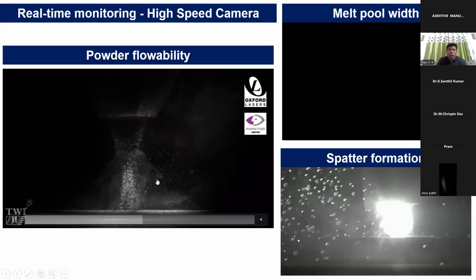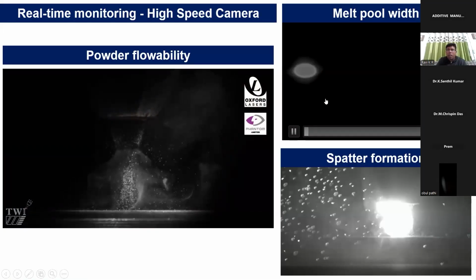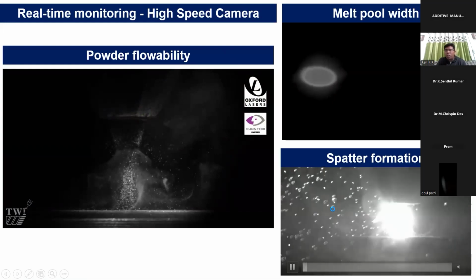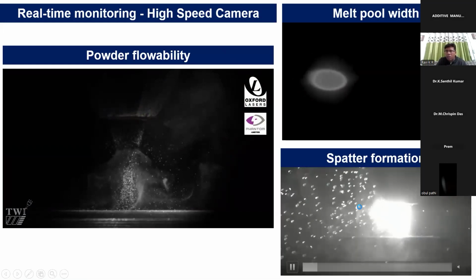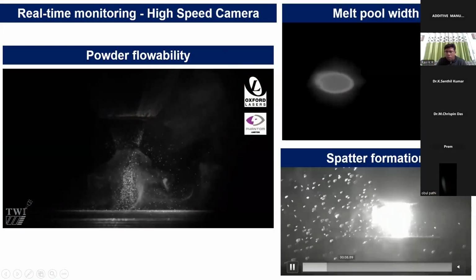Okay, now let us look at real-time monitoring. This is real-time monitoring where we use a high-speed camera. One can get the powder distribution, powder size, and the flowability. One can understand the melt pool width using a high-speed camera. The spatter formation one can understand using this high-speed camera. These are our own results.